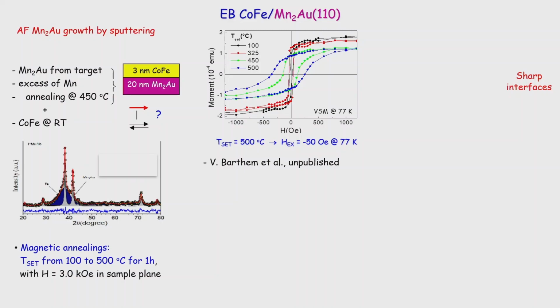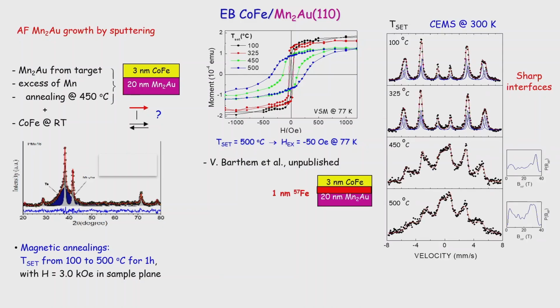And we did that, and we see that after annealing at 500 degrees, you get a small exchange bias. And to see what happens at the interface after the annealing at this temperature, we did also Mössbauer by putting 1 nanometer of iron 57 at the interface between these two materials. And then we see that we have a really very flat interface, so only after starting from 450 degrees, we start to see a change in the spectrum, okay?